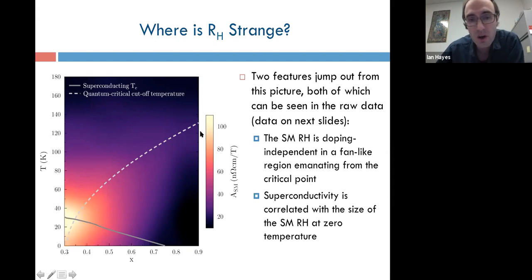So this is striking. There aren't too many experimental observations that paint the fan quite this clearly. So this is fairly striking evidence in favor of the idea that this effect is coming from the influence of the nearby ordered phase. The second thing I want to draw your attention to is what happens at low temperatures.